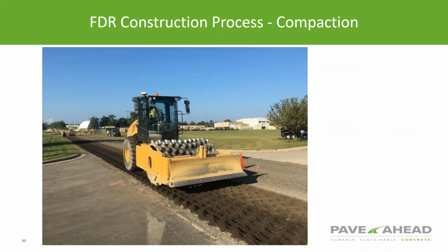Typically, you're going to see a pad foot compactor, preferably with a knockdown blade, so you can roughly back drag and keep that platform that the compaction is happening on uniform, so you don't have a big hump. Because if you got a hump in that soil or aggregate, and you got a 7 or 8 foot wide drum, but you got a 4 foot wide knob in the center, you're only getting compaction in that center 4 foot. You're not getting your outside edges. And that's typically for the deeper depths. If you're doing shallow FDR at, say, 6 inches, all in aggregate, you probably just get by with a base roller, a smooth drum type roller, for your initial compaction.